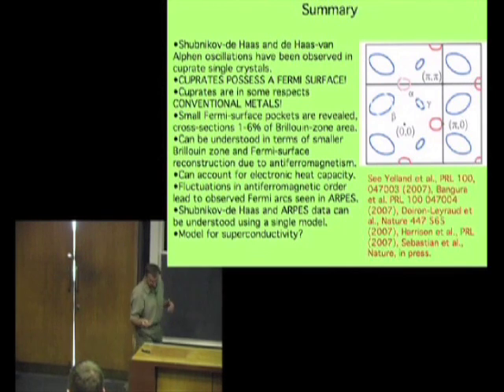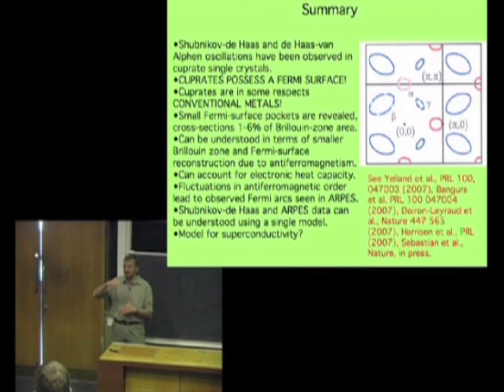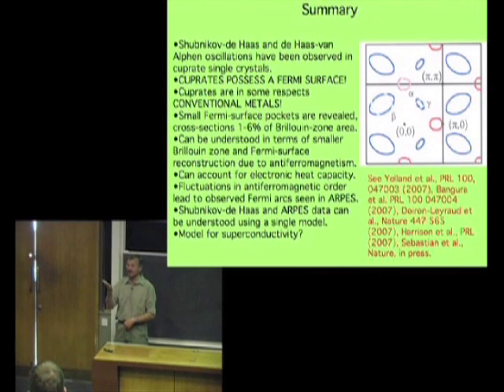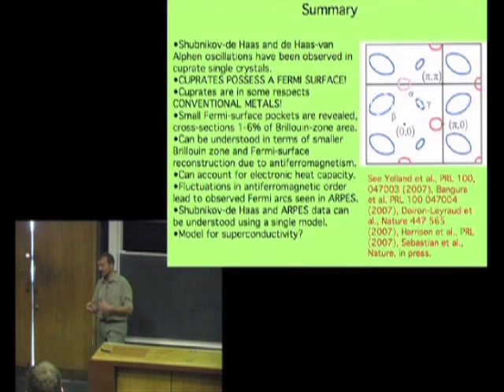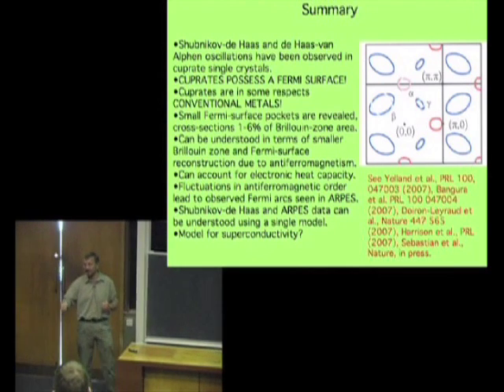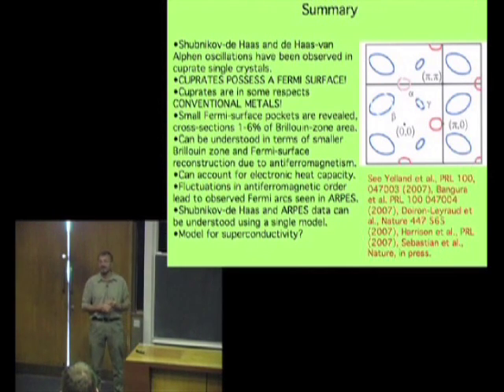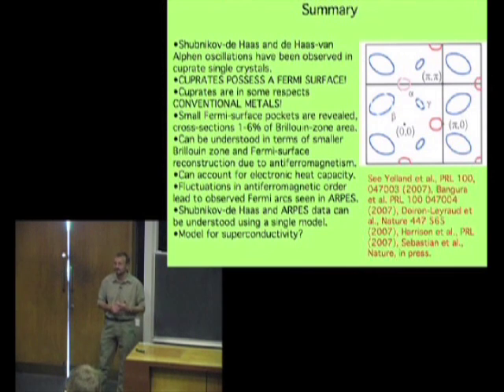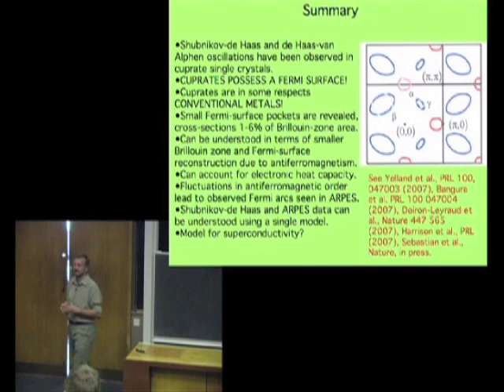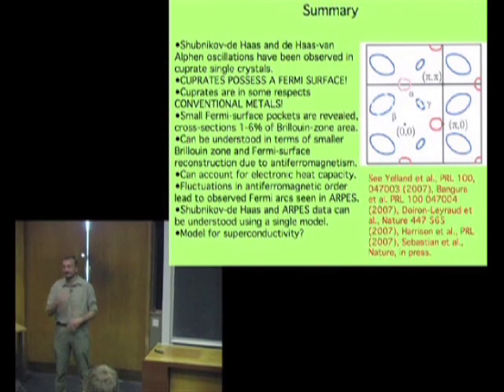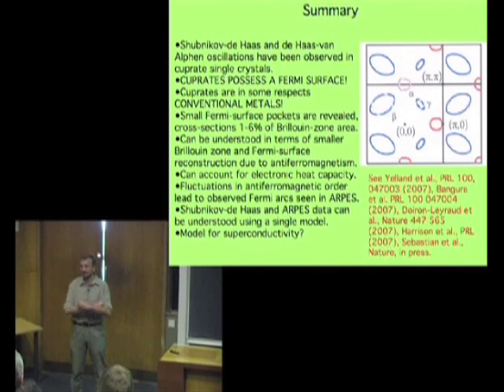But in some of them, the electron-phonon coupling constant is a little bit higher, or you're at some sort of commensurability where the CDW can lock on very, very stably, and then the charge density wave-like order, the stripe or checkerboard or whatever, will win, I think. I think it's a delicate balance in the cuprates. But even in the yttrium-bearing cuprate, there's evidence for stripes at certain filling factors. In other ones, they're just more dynamic rather than static.